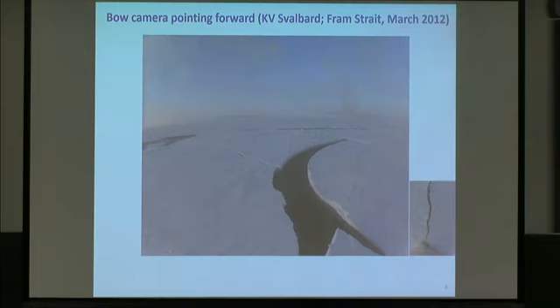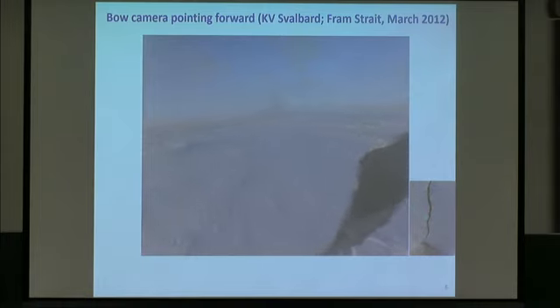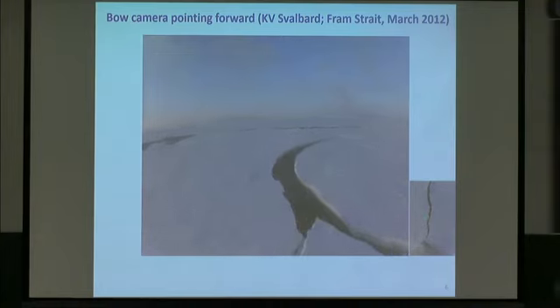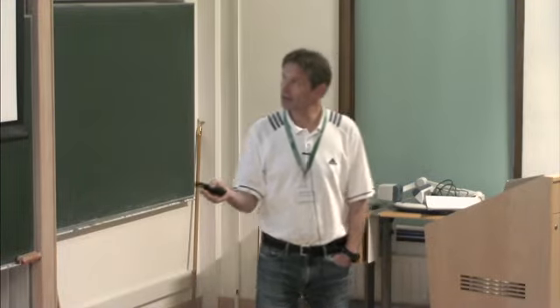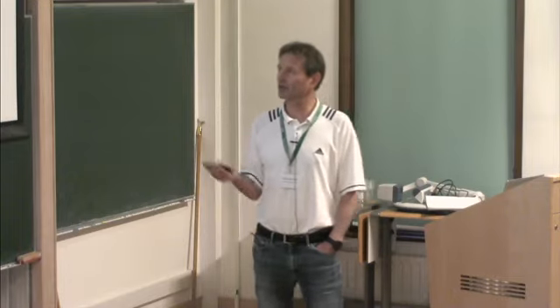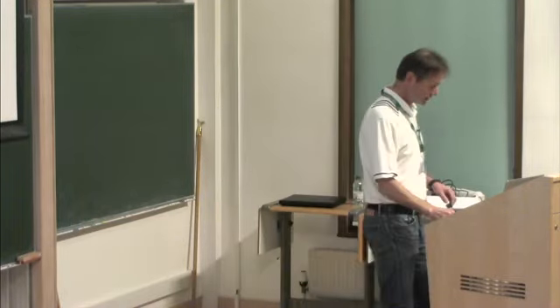And what was characteristic and what I said was that there is lack of confinement on this. It was just as you saw on the previous slide. Now we are running into it. And you hear the rattling. Can you hear it? And then we come. The temperature here is low. This is up in the Fram Strait in 2012. But what I would like to say and stress, I see this kind of failure both in cold ice and in warm ice. So even if we had minus 30 here, this could very well happen at minus 5 and minus 8 and so on as well. So that's what we see.